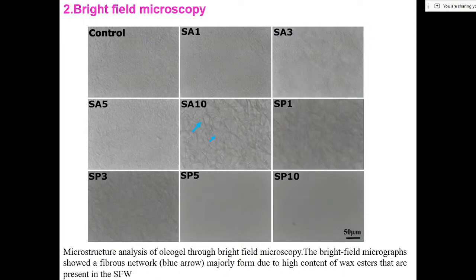Then again we went for the bright field microscopy. If you see, some fiber like structures are being formed over here. And as we are increasing the concentration, at SA10, long fibers were formed, and in between, the voids were quite high. So when we analyzed this SA based system, we were able to see the microstructures to a certain extent. That was very appreciable. However, when we were analyzing these SP based categories, especially SP5 and SP10, we were not able to see any distinct microarchitecture within these two samples.